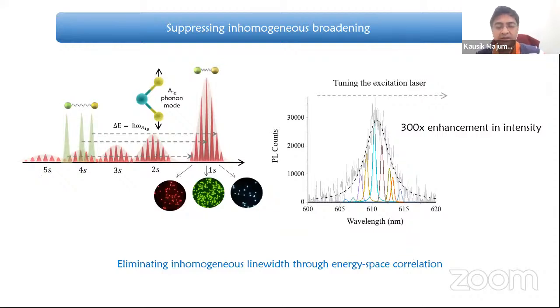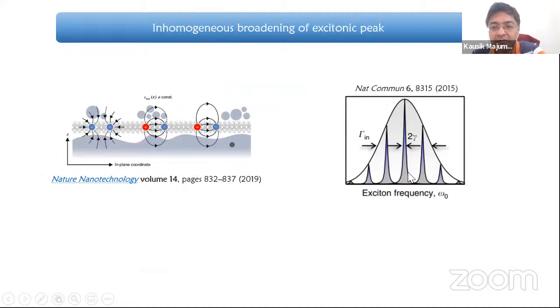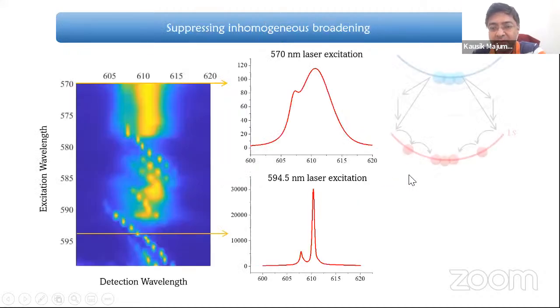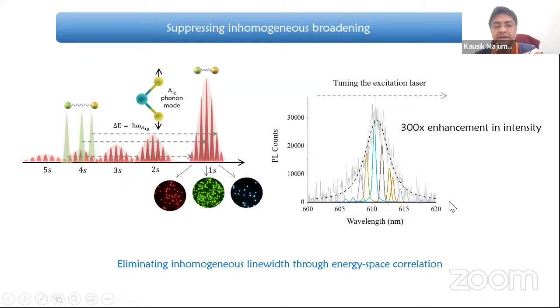Why the line width narrows down is a big story, and I don't have the time to explain it, but basically you are resonating between those spots which match your excitation and luminescence separation. So you're picking up only those spots, and there is a very strong energy space correlation. You can see this is the off resonant excitation, and this is the tunable, resonant excitation. So you are actually able to experimentally make what was predicted 5 or 6 years back.